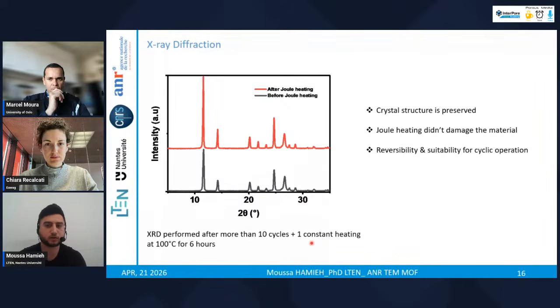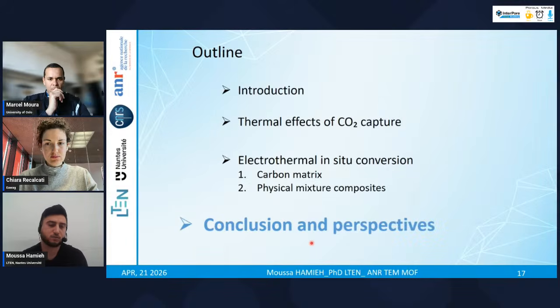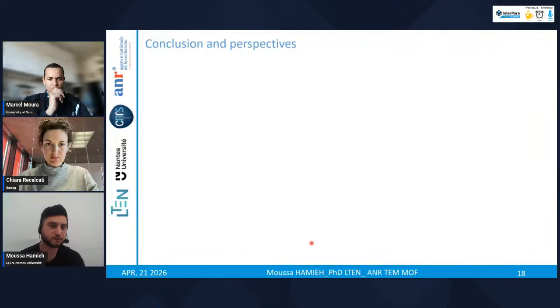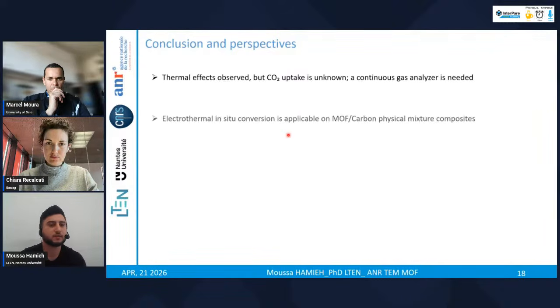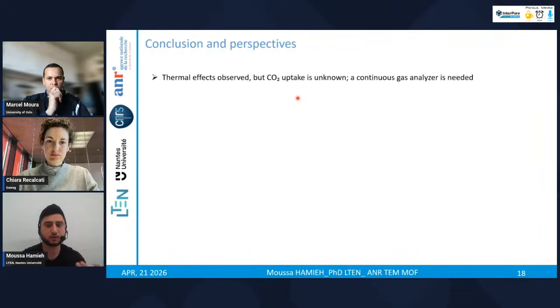So after confirming the thermal effects and also the electrothermal conversion, and that the material remains stable after these cycles, now I will summarize the main results and perspectives. First, we confirmed that thermal effects occur during CO2 absorption, leading to a temperature increase. However, the CO2 uptake is still unknown, so the gas analyzer will be needed to correlate the results between temperature change